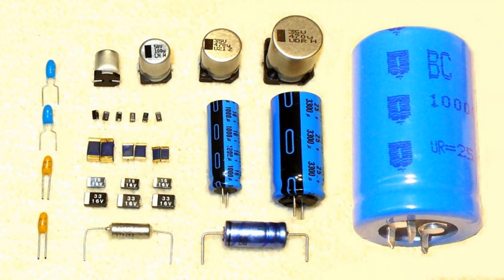But a great difference exists in the case of wear-out failures. Tantalum capacitors with solid electrolyte have no wear-out mechanism, so that the constant failure rate is valid up to the point when all capacitors fail. Electrolytic capacitors with non-solid electrolyte, however, have a limited time of constant random failures up to that point when the wear-out failures start. This time of the constant random failure rate corresponds with the lifetime or service life of wet aluminum electrolytic capacitors.